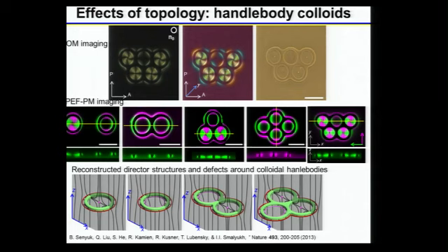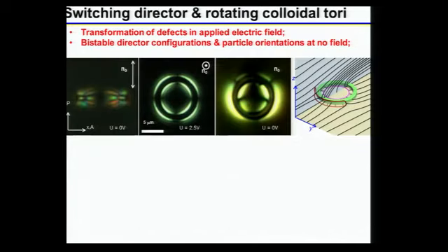Now you can see already from those images and from those cartoons I show in here that we induce topological defects. The magenta and red colors in here depict the defects of opposite signs, right? So pluses and minuses. Now, different defects obviously appear depending on the number of holes or genus of those colloidal particles. And what's interesting is that we can use external fields of different kinds, laser beams, or, for example, apply an electric field and rotate those particles or switch between different multi-stable orientations.